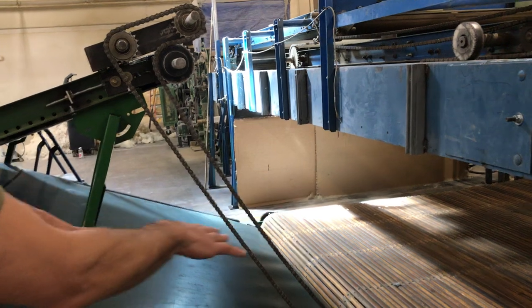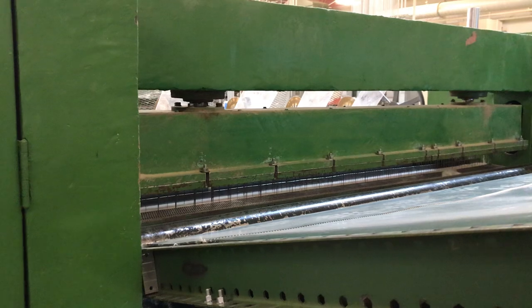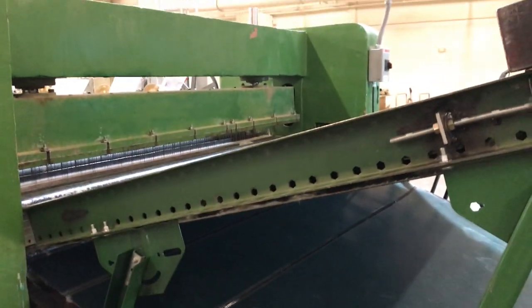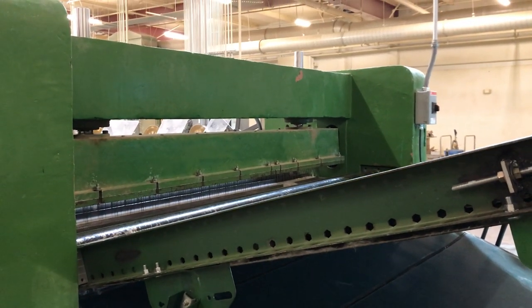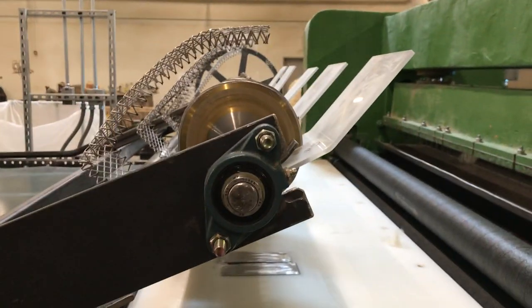The bat line isn't running now but basically the wool comes in as a really thin film and this machine — called a cross lapper — flakes it down slowly. Then you've got a couple hundred needles with barbs on them. Instead of glue — most people use formaldehyde-based glue, which is a no-no for us — we stitch the bats together with their own fibers. This machine sews the bats together using a needle-punching process.